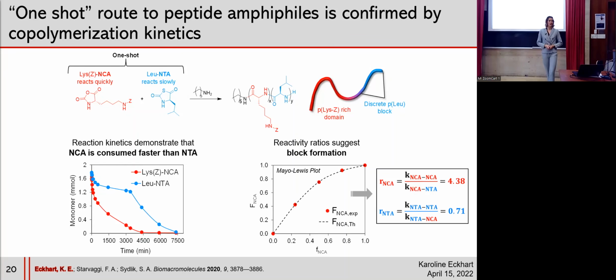As another measure to evaluate the blockiness of the peptides, we looked at the reactivity ratios. So by comparing the copolymer composition versus the comonomer feed ratio, we could fit that experimental data to the Mayo-Lewis equation and give reactivity ratios. This means the ratio of the rate constant of homopropagation to cross propagation. And what we found here is that the NCA monomer has a reactivity ratio much greater than 1. And this means that when both monomers are in the solution, we get preferential propagation of the NCA over the NTA. And that the reactivity ratio of the NTA is less than 1, which means that even if an NTA just added to the polymer chain, it prefers adding another NCA on top of that.